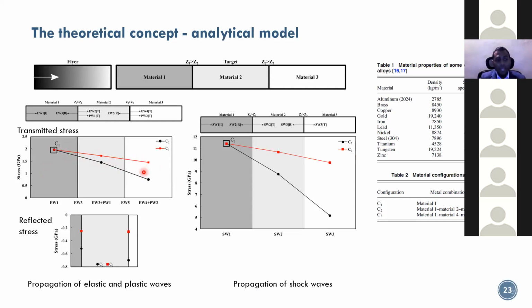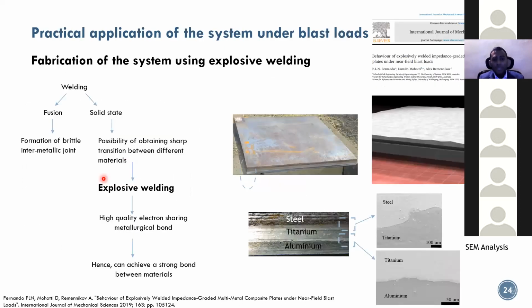So what this tells us is, to maintain high impedance reductions within the system, you can significantly reduce the transmitted stresses onto a structure. But it comes at a cost. What this means is it has to reflect stresses at each joint, and it's these reflected stresses that can cause delamination between these multi-materials. So when you have more than one material in a system, you are susceptible to what's called delamination. To avoid that, we need to make sure that once again we strike the right balance between how much we want to transmit and how much we want to reflect. So this was the basic concept that I proposed in the PhD, and specifically in relation to blasts.